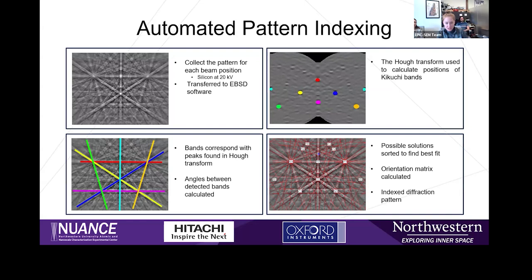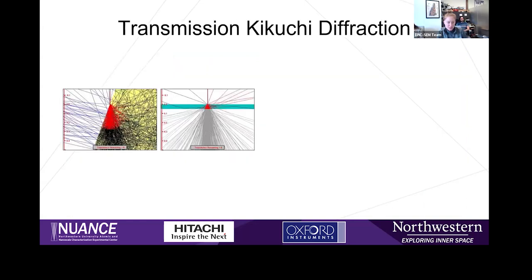orientation. Many of you, if you do EBSD, probably do traditional EBSD where you use a bulk material, and there are limitations when doing EBSD with bulk materials. Of course, polishing: you need to have a pristine surface. But you can also see in this cross section right here, and this is your 70-degree tilt sample, and we talk about in our SEM trainings, your interaction volume. When the beam interacts with the sample, it scatters and you get this large region or large surface where signal is being emitted.